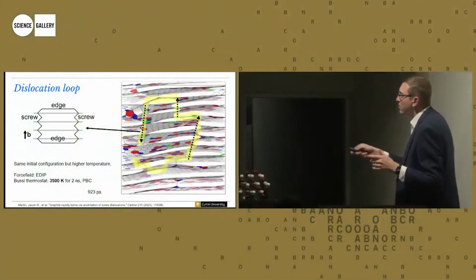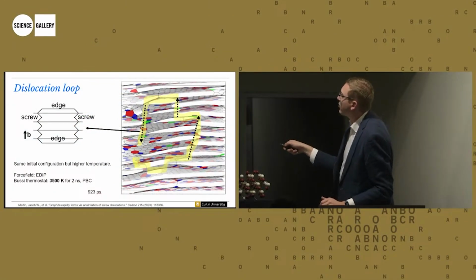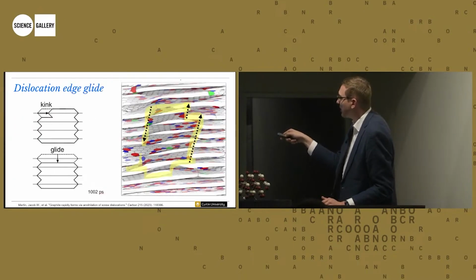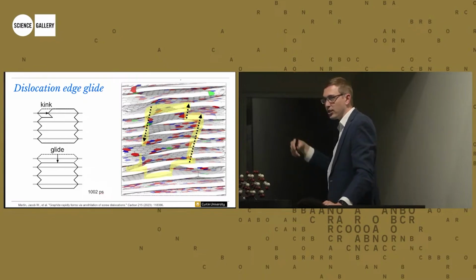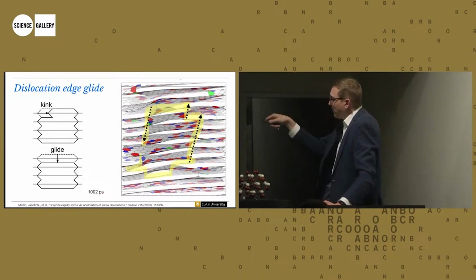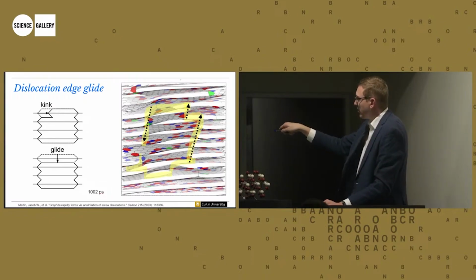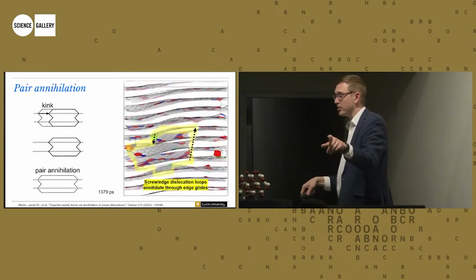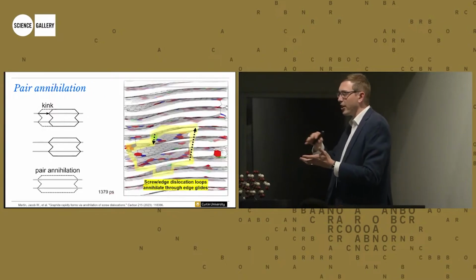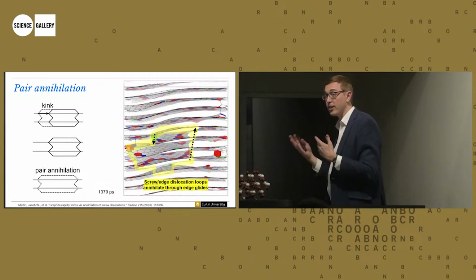And so when we played the video, when we actually went through this, we found that you form a kink here, and then it runs along, the edge glides, and then it frees the sheet above. And that keeps going until you're down to the 2 layers that I've 3D printed there. And then when they go, you've completely removed it, sort of unraveled.